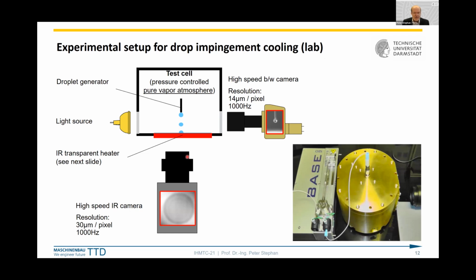In the drop impingement cooling experiment, we developed a test cell. Inside this test cell, we can control the vapor atmosphere with pressure, so it's a pure vapor atmosphere in this test cell. We have a small droplet generator which can create single droplets.